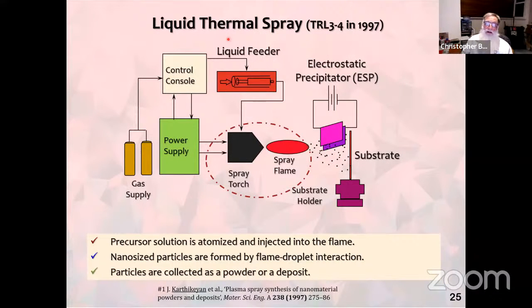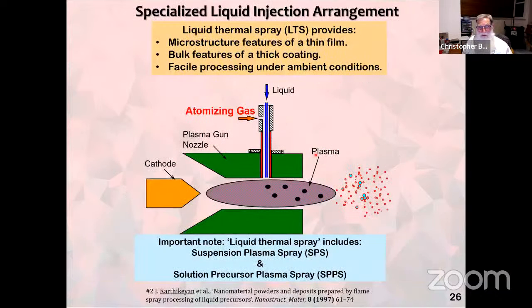So liquid thermal spray is a potential technique. In liquid thermal spray, we put a solution, a liquid, into a pump, we feed it into a torch, and we can either get a powder or we can get a coating on a substrate. What is happening within the torch is that we have particles travelling along and forming nanoclusters. It is important to note that liquid thermal spray includes suspension plasma spray and solution precursor plasma spray.